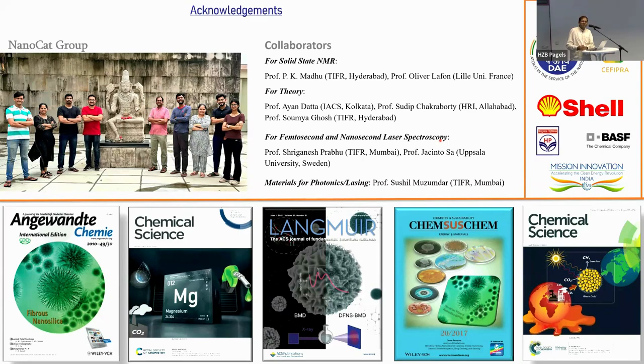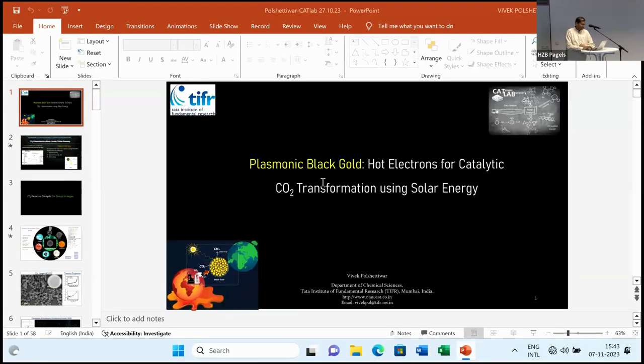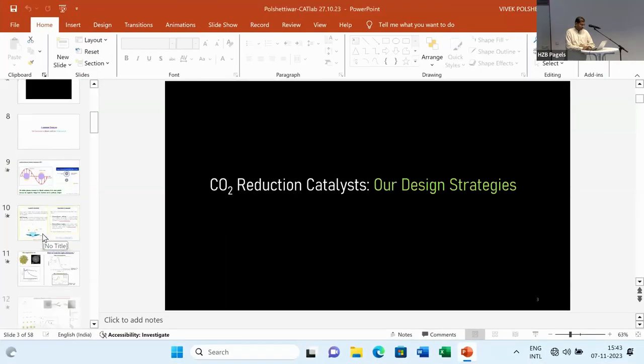Okay. I also have a couple of questions. You spoke about this nickel getting oxidized when you're exposed to the atmosphere. So this could also happen when you're doing the reaction, right? When you start with your gold or nickel nanoparticle, maybe the 5 nanometer surface is oxidized and you're directly using the reaction conditions. Did you check, before catalysis and after catalysis, with XPS or any other methods, whether they're already transformed in the beginning? Because although it's metallic, the surface could be non-metallic. Let's say you have some oxo species on the surface.